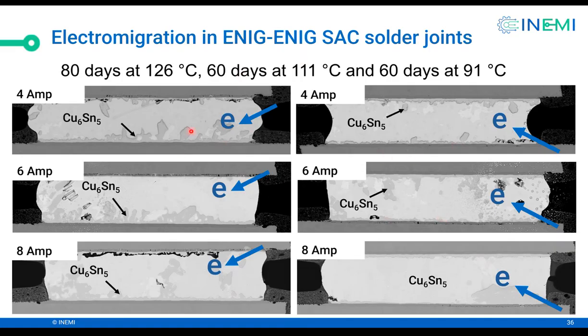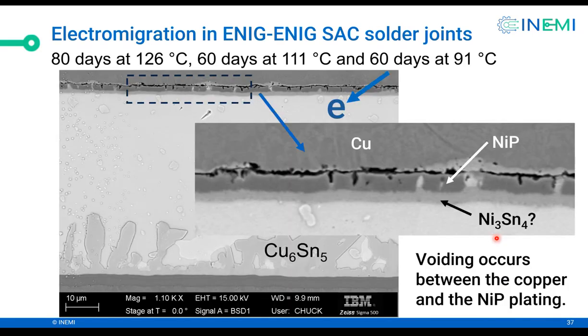Here you can see a lot less Cu6Sn5, but it's still plenty. And that's because of the nickel diffusion barrier. And you do see voiding here. You see voiding here. And the voiding is there, but we don't see it in the rest because the magnification is low. So let me show you a picture at high magnification.